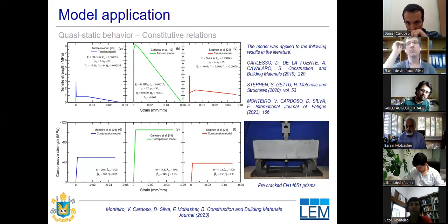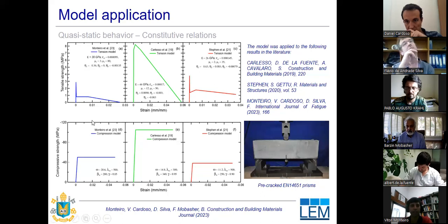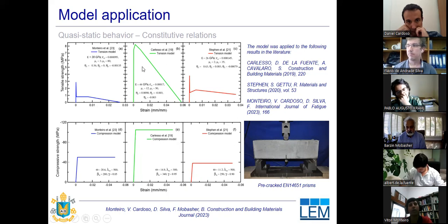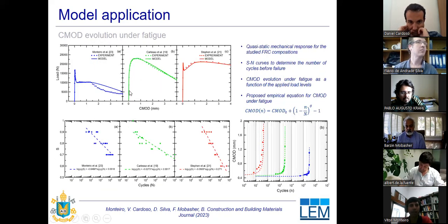So now I'm going to bring the application of this model workflow for some results in the literature. We have the tensile strength for the results from Monteiro, Carlesso, and Stephen. We applied the constitutive models on the tension and compression. So we have here the plastic elastic compression model, and the quad linear model in tension for the studied authors. After that, we can verify if, after using the constitutive models, they have good fitting with the experimental results in terms of load-CMOD for the studied authors.